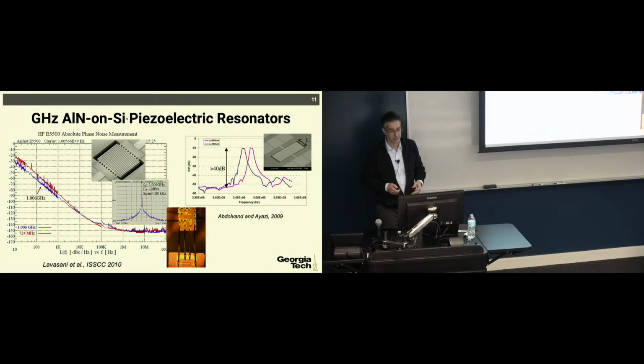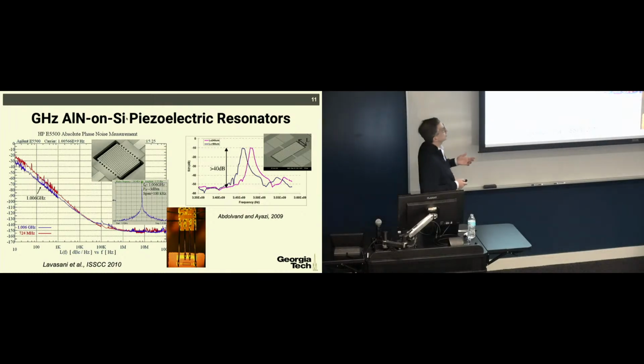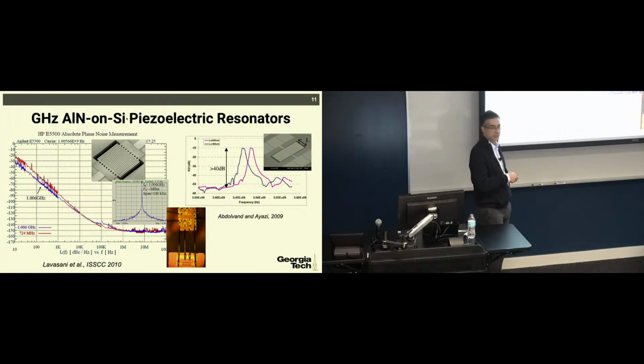much longer lifetime. Now, gigahertz resonators also became available in a way that was usable for industry because of the aluminum nitride piezoelectric films. So this is an example of a resonator using, again, aluminum nitride as an actuation layer. You see that this device was resonating at 1 gigahertz, and the oscillator that was made by interfacing the resonator with an IC showed a very good performance level that was suitable for most of the communication systems being used.